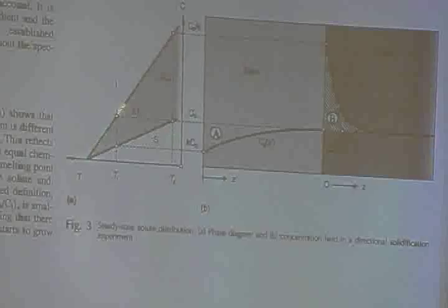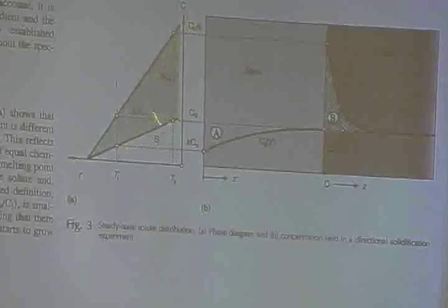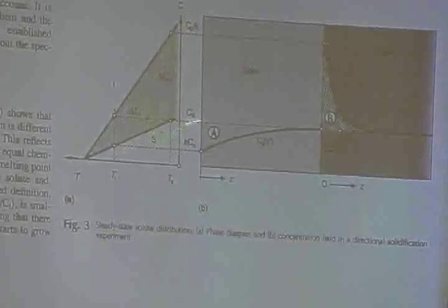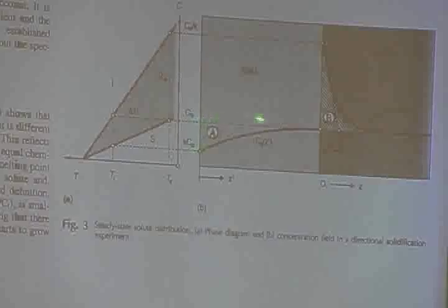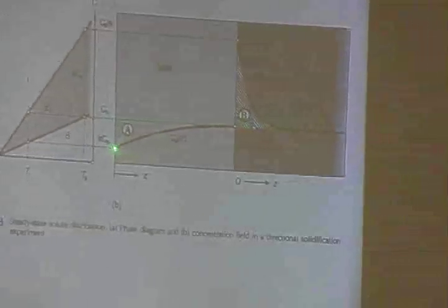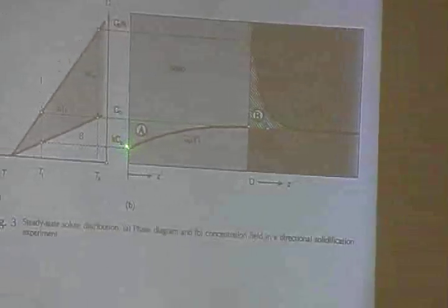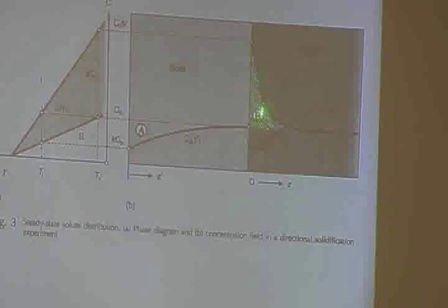Here's the melting point, here's the solidus line, here's the liquidus line. If you map that turned 90 degrees onto this concentration, here's your C0, your average concentration, and here's your KC0, the first solid to solidify. As you go along here, you're pushing the solute ahead in the liquid, and you actually have a boundary layer you can start analyzing.